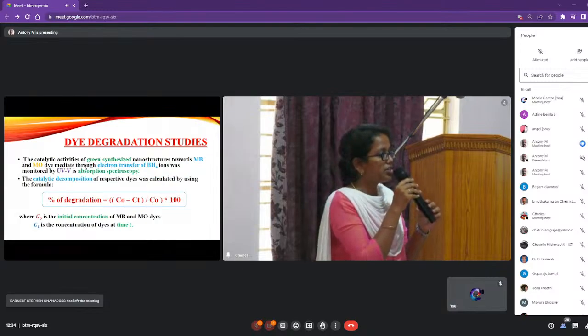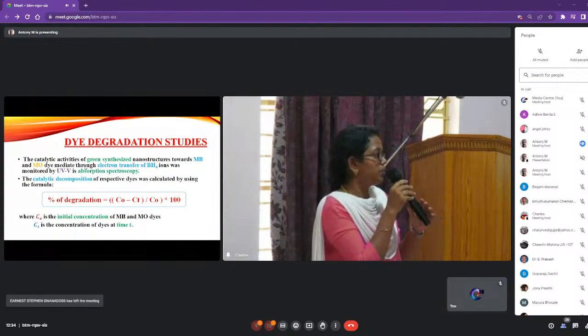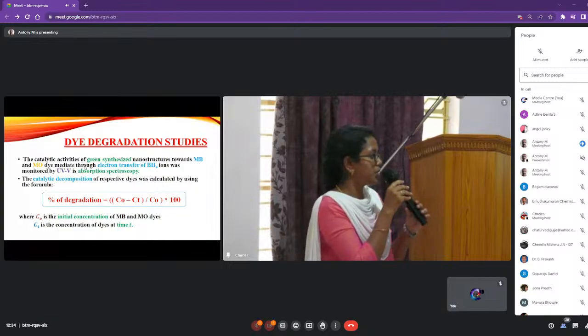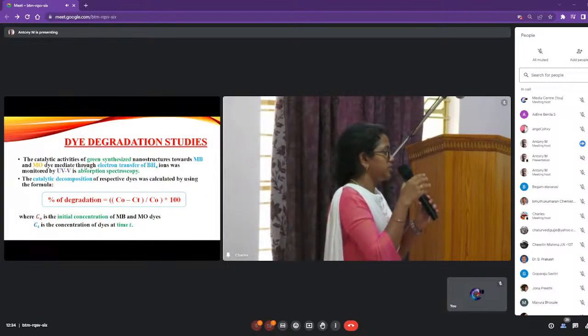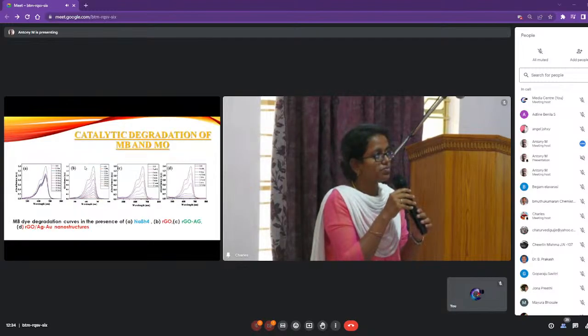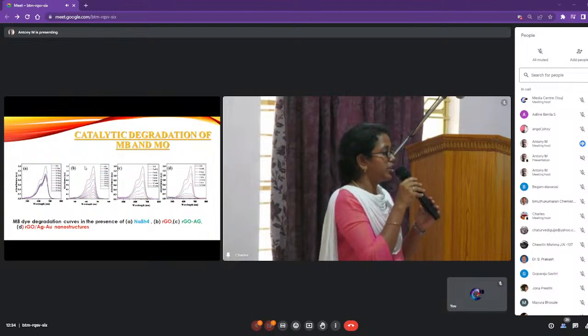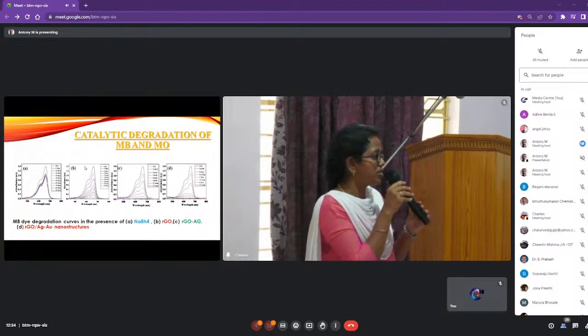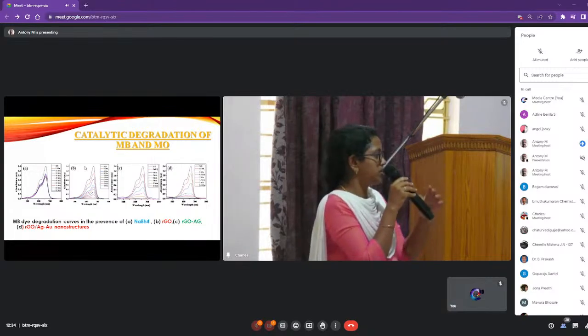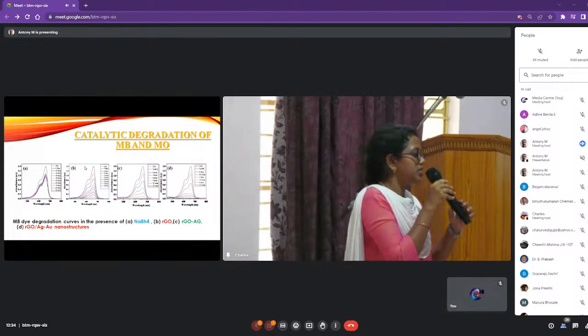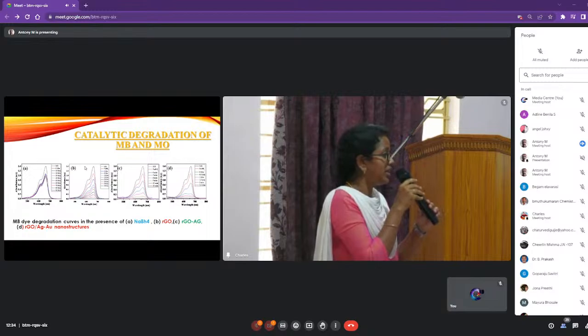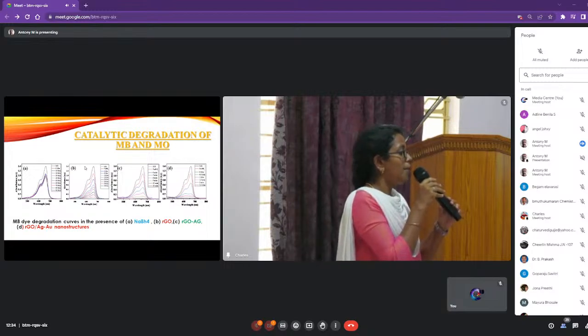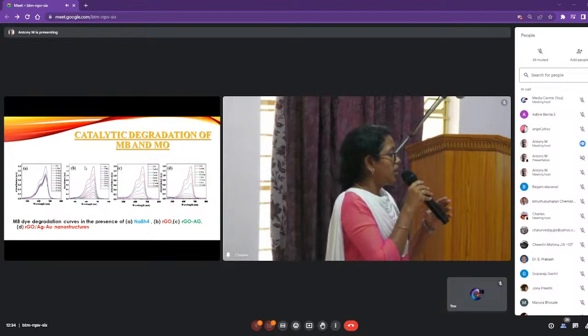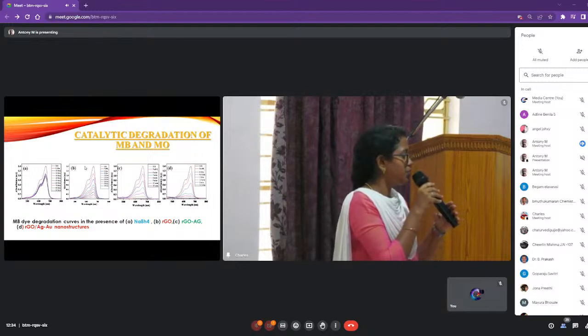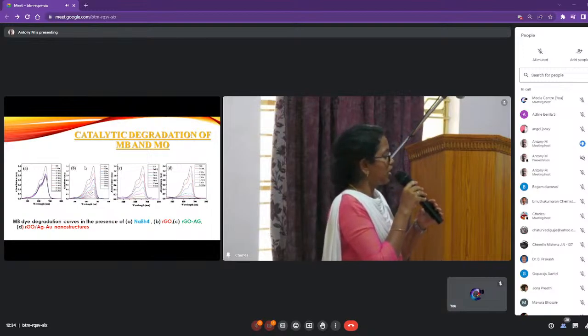So the degradation is studied for methylene blue and methyl orange using the UV spectrometer, and the percentage is calculated using this formula. So now the catalytic degradation of methylene blue and methyl orange is shown in this curve. The first curve indicates the degradation process of methylene blue by adding NaBH4. If we do it only with the NaBH4, the degradation process takes around 90 minutes.